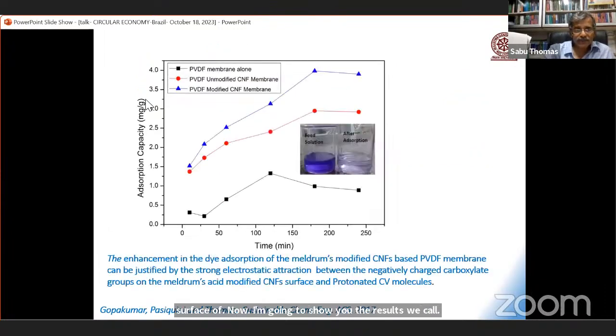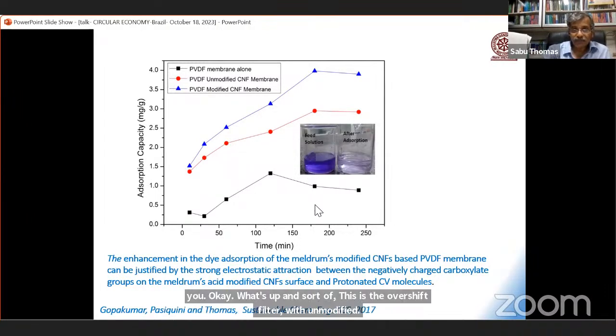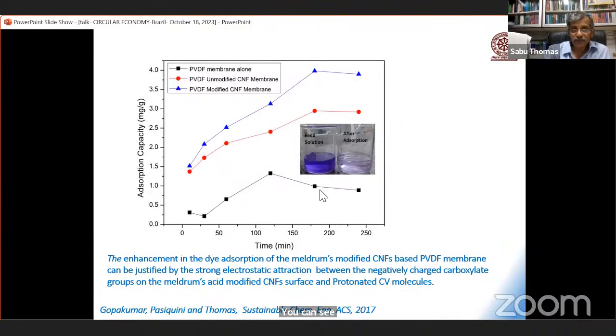Absorption capacity of the crystal violet dye, milligram per gram, as a function of time. We went up to 250 minutes. Look at this, this is the commercial filter that you get in the market. You see, the behavior of the commercial filter goes up and sort of levels off. This is the commercial filter coated with unmodified nanocellulose. You can see the filtration efficiency has gone up. It was 1 or 1.5 and became almost 5 with the coating of nanocellulose.